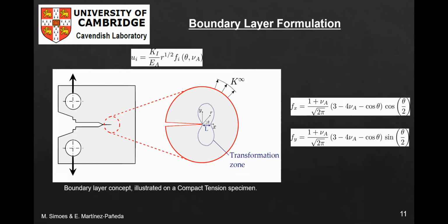So the first boundary value problem is what we typically call a boundary layer formulation. And our goal is to compute crack growth resistance curves, or so-called R curves. The concept of a boundary layer formulation is illustrated here. For a cracked solid, the crack tip stress state is characterized by the stress intensity factor K_I, assuming mode I conditions. So we prescribe a specific stress intensity factor by modeling a circular region and prescribing on the outer boundary the displacements according to the Williams elastic solution. Remember that the high stresses near the crack tip will trigger a phase transformation, but as long as this transformation zone is small, this approach can be used.